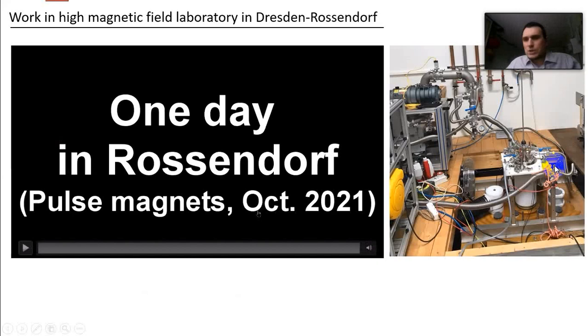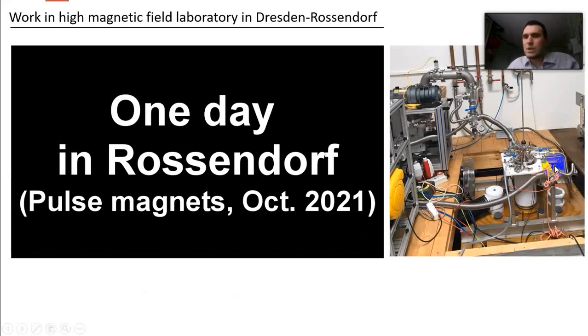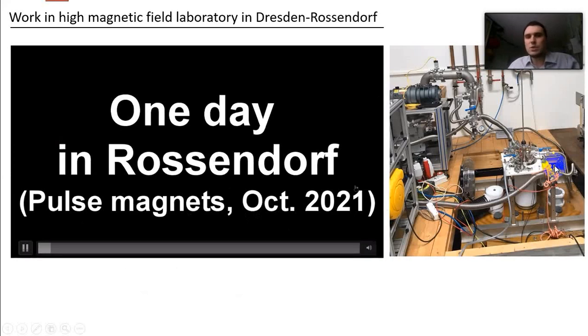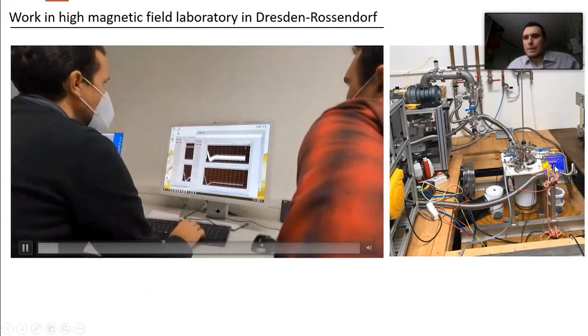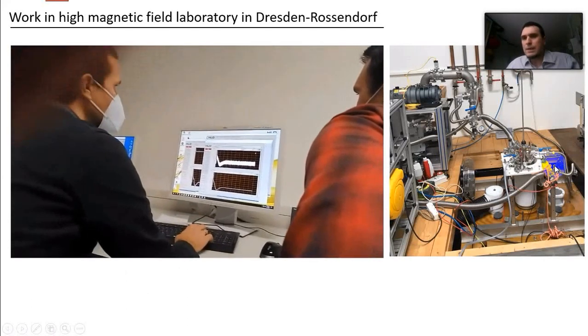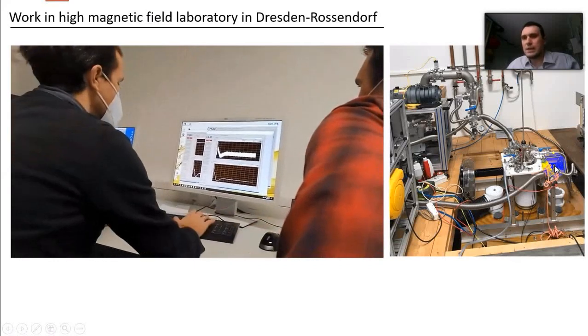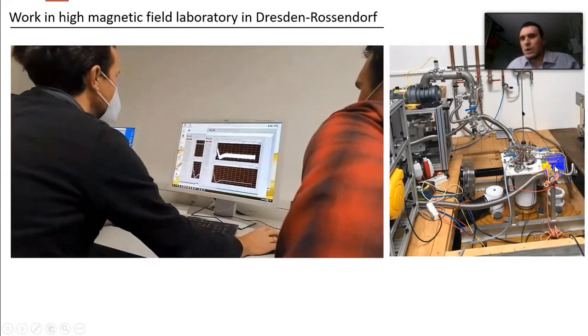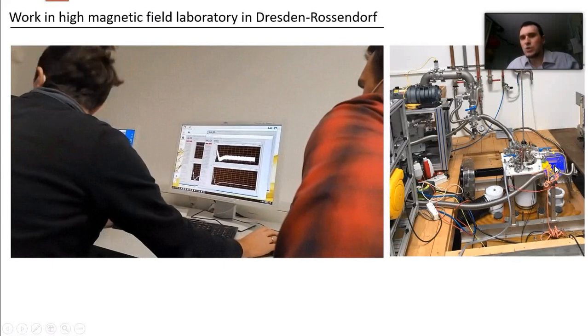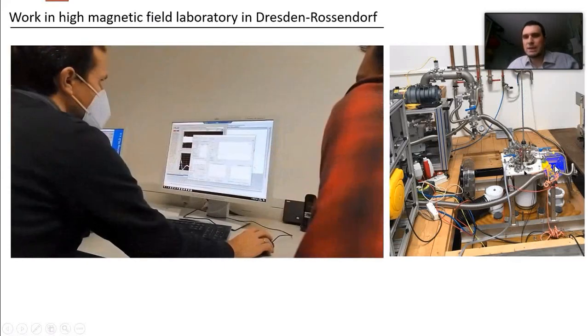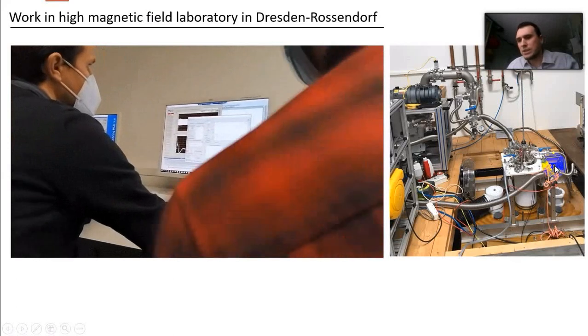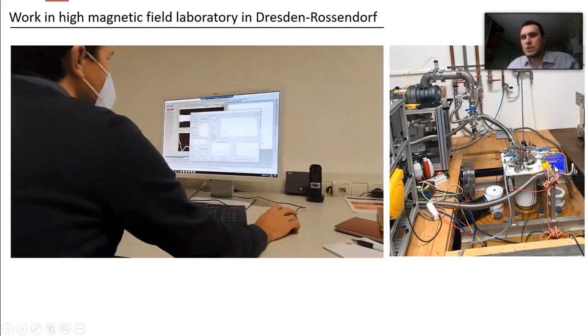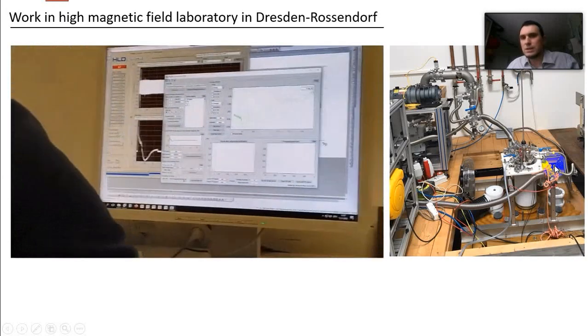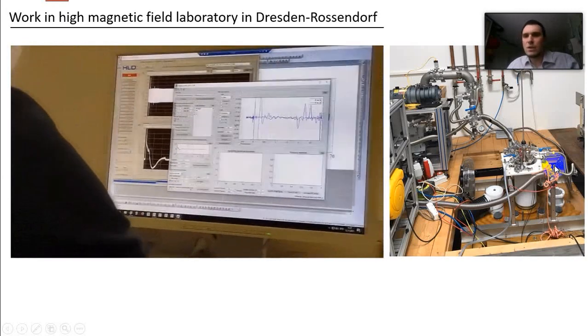Okay, finally, I would like to show something about the pulsed magnetic fields. It's an important investigation now. So we used pulsed magnetic fields in Rossendorf in Dresden, Germany in October 2021. It's a complex system. The magnet you cannot see, it's underground, and it has a very narrow channel to put the diamond anvil cell with the sample. And after that, it should be cooled to liquid nitrogen temperature. And we control the temperature of the sample by flow of helium. You see here the vacuum and the helium tubes.